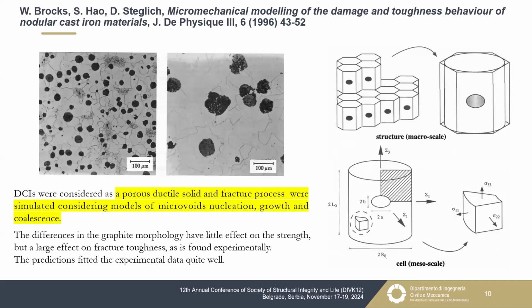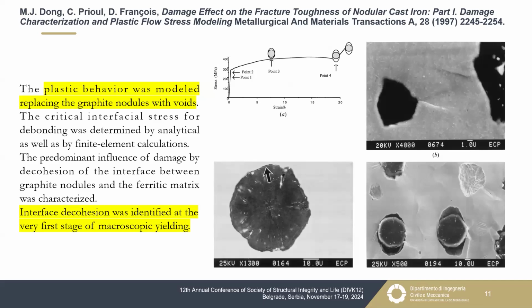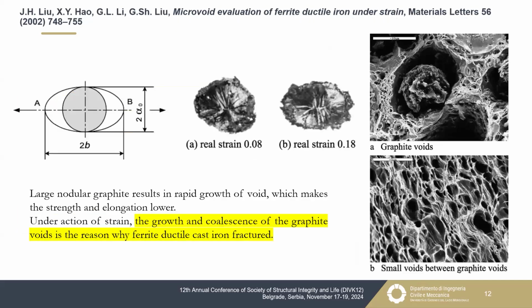By considering a numerical approach, they found that the simulation of microvoid nucleation and growth equations was able to predict very well the mechanical behavior, the tensile stress curve in these alloys. Also, analyzing the damage mechanism, focusing on decohesion, it was possible to simulate the interface decohesion between matrix and nodules, finding that this was the predominant damaging mechanism.